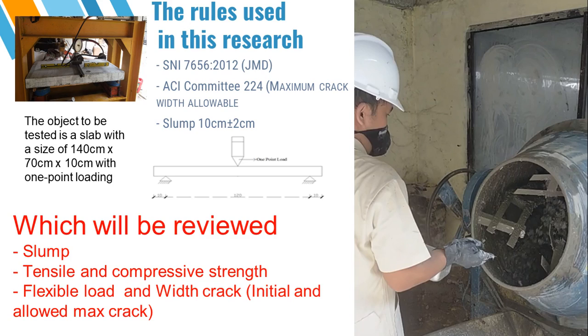For the concrete mixture, we review slump, tensile and compressive strength, flexural load and crack width, and initial and maximum allowed cracks. For the flexural load and crack width, the test object is a slab measuring 140 centimeters in length, 70 centimeters in width, and 10 centimeters in thickness, using one-point loading. The rules used in this research are SNI and ACI for maximum allowable crack width, and a slump plan of 10 centimeters plus or minus 2 centimeters.